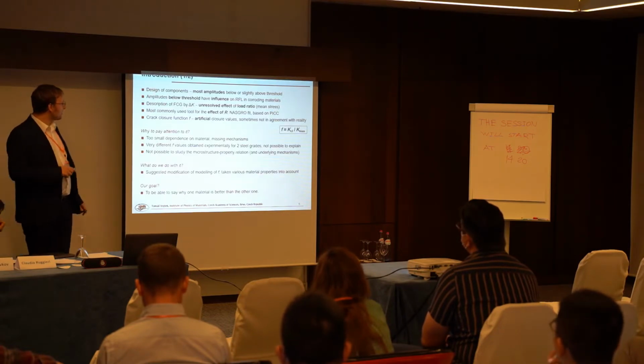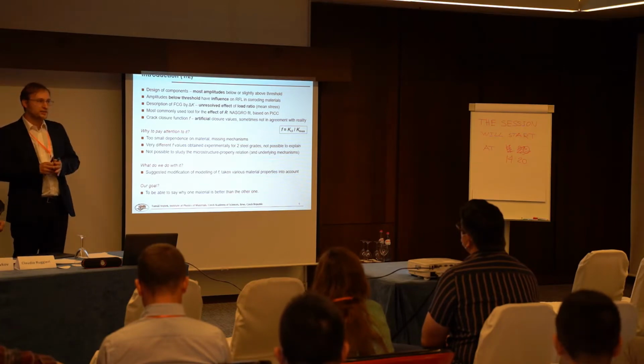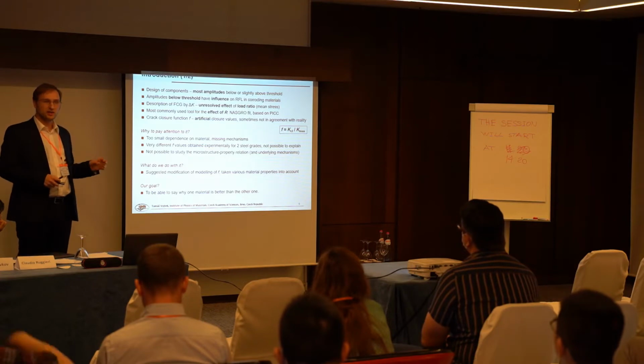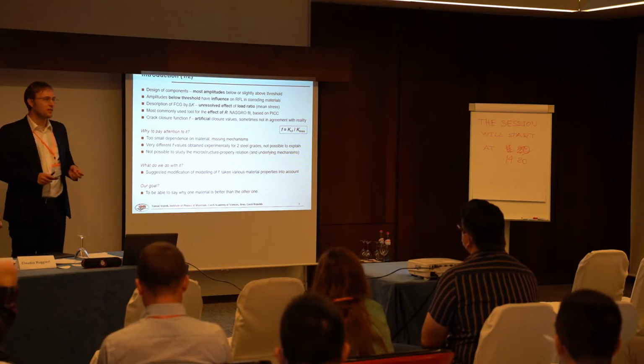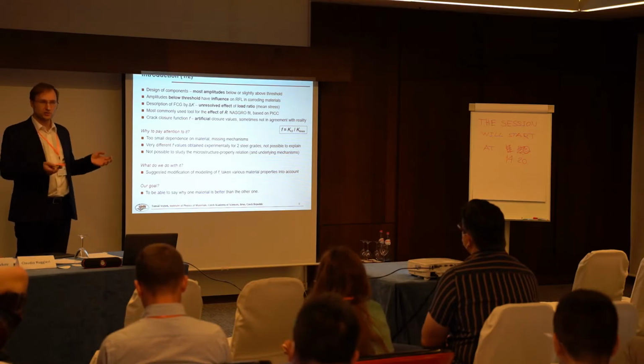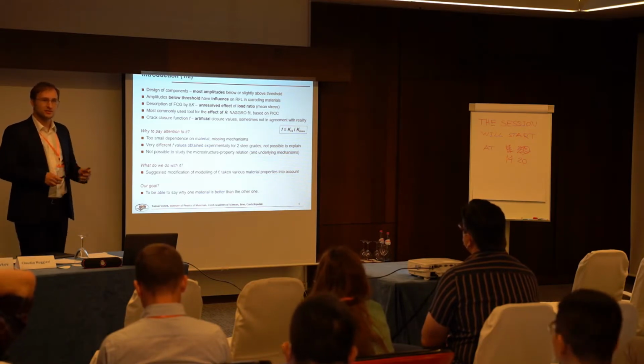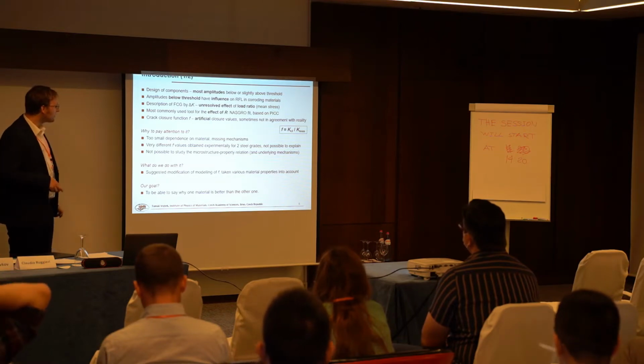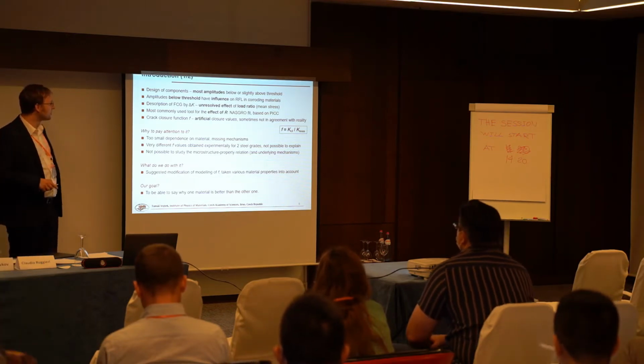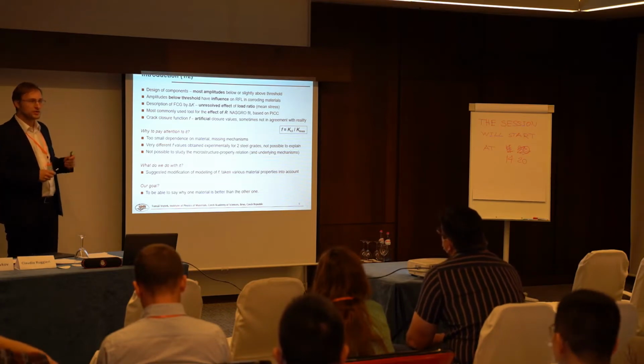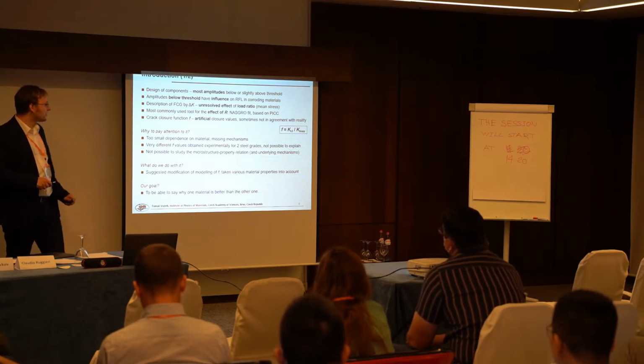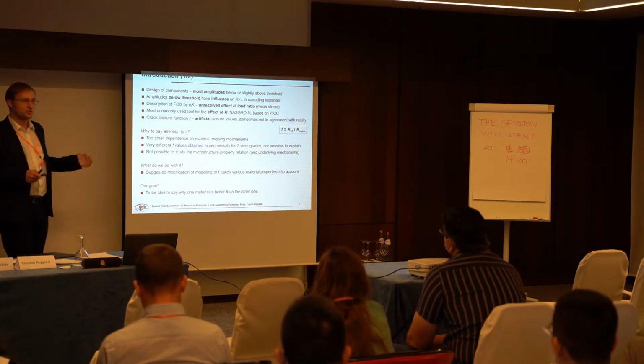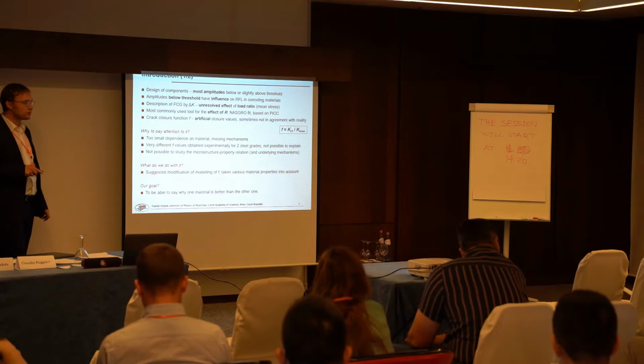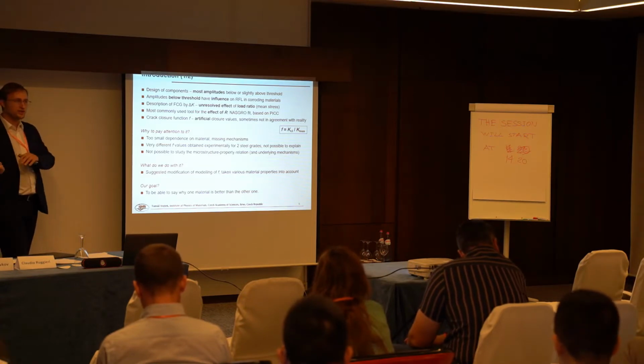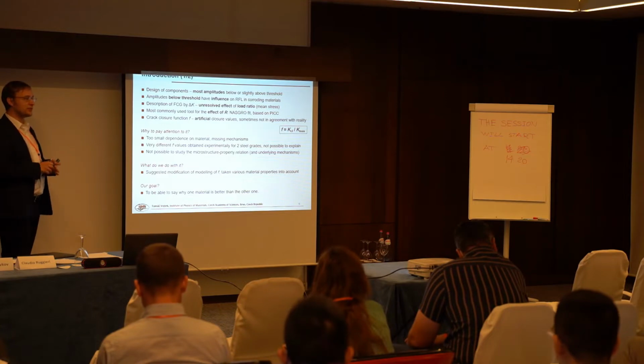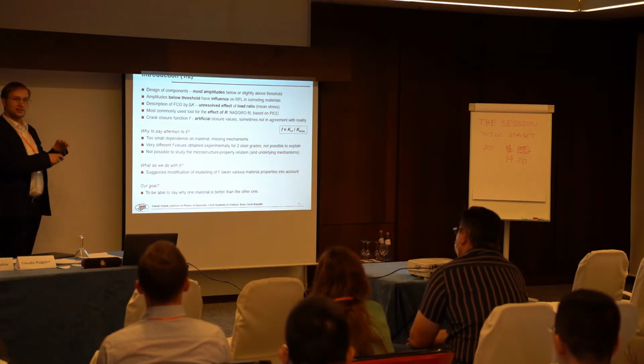So this is what I said. Fatigue crack growth rate is usually described using the stress intensity factor range, delta K, but we still don't have a reliable description of how to deal with the mean stress, so the load ratio effect. So one of the tools that is usually used is the fit by NASGRO, which takes into account plasticity induced crack closure. But actually the value of crack closure predicted by this scope is not always in agreement with what we find in reality. And we think that it is because it completely ignores the microstructure and the material side of the problem.